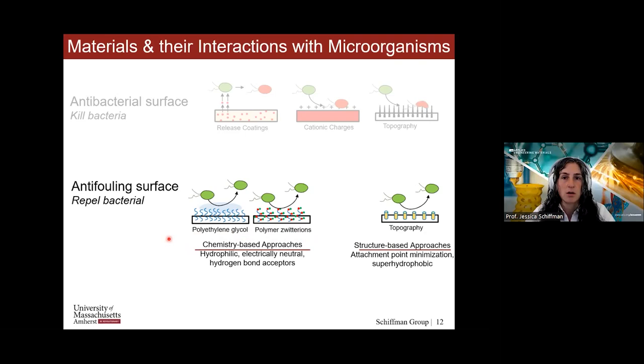How does this work? Well, in these cases, we have a very hydrophilic surface. And of course, other hydrophilic polymers have also been shown to be anti-fouling. But in this particular case, the hydroxyl groups on the polyethylene glycol actually make a water shell. And the bacteria would have to move into that shell in order to get to the surface, or move away that water coating. Same thing with the polymer zwitterions. Here in this cartoon, I want you to imagine that our red dot is a cationic charge and our green dot is an anionic charge.